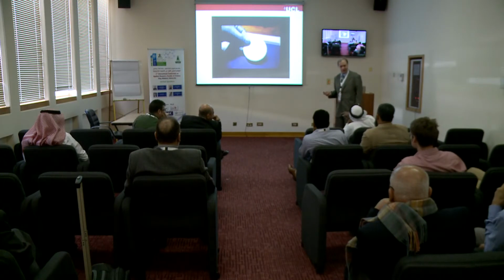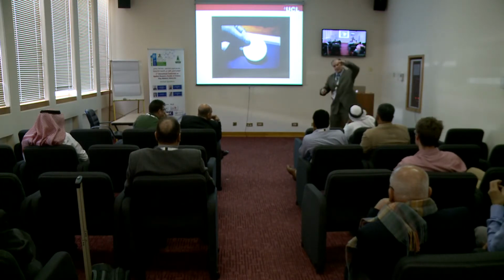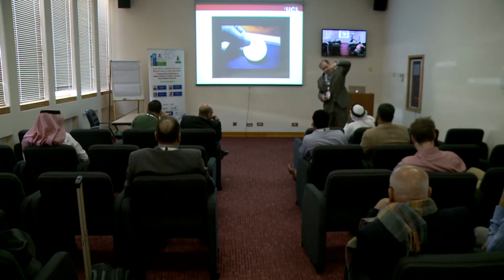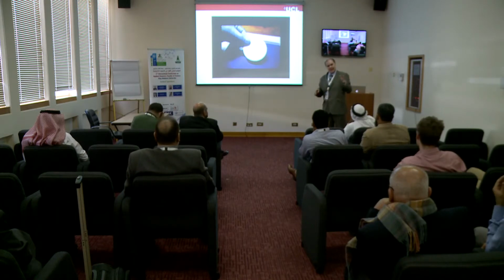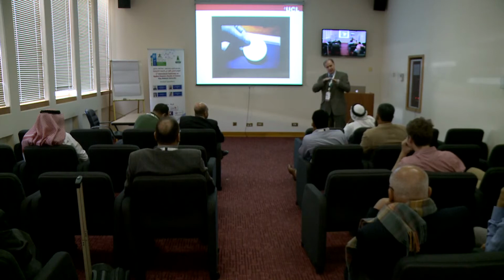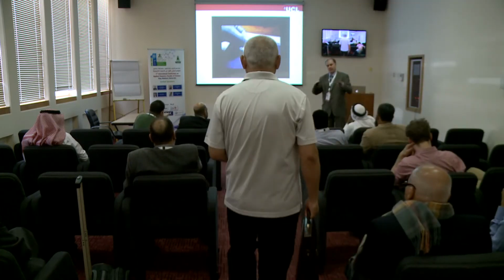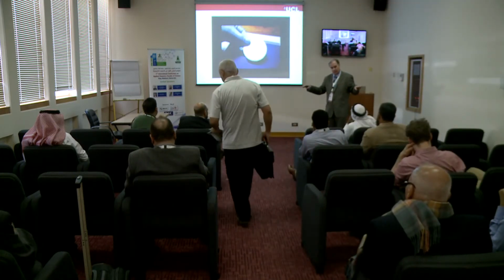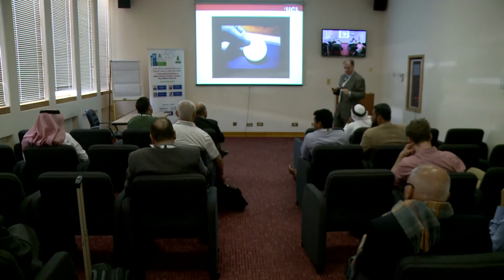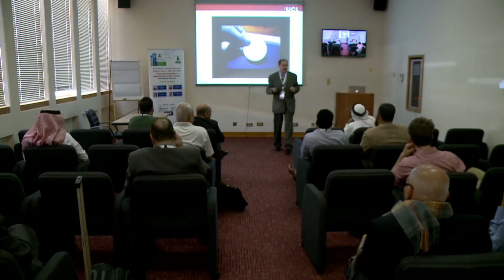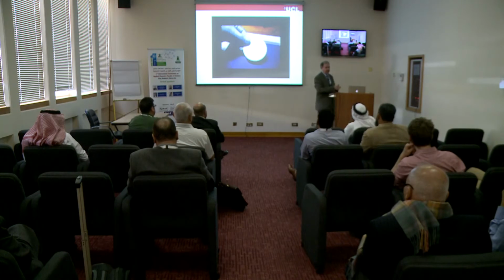Can I interrupt? You can interrupt. What determines the number of bounces? The number of bounces is determined by the static contact angle. So the more marble-like it is on the surface, the more bounces you have. The way we do that is to control the surface microstructure by making it rough and also having a water-repellent surface. We have a polymer surface which hates water. By combining the polymer surface which hates water with the roughness, we get the bouncing. Has nothing to do with the thickness? No, nothing to do with the thickness whatsoever.